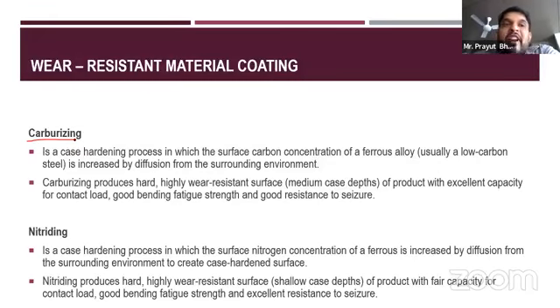Similar to carburization, there is nitriding. Nitriding is a case hardening process. Again, it's the same as above, but in this the surface nitrogen concentration of the ferrous alloy is increased. So similar to the carbon, in this case we use nitrogen. Again, it gives a hard, highly wear resistant surface with fair capacity, with the same properties as above. But in both processes, you need to understand that one is mentioned as a shallow case depth, and the other is a medium case depth. This is important. It means the depth to which it is deposited and can act as a wear resistant surface is medium in the case of carburizing, and shallow in the case of nitriding, just on top of the surface. So once that shallow layer is removed, you get the parent material again, and it will not be a wear resistant surface.